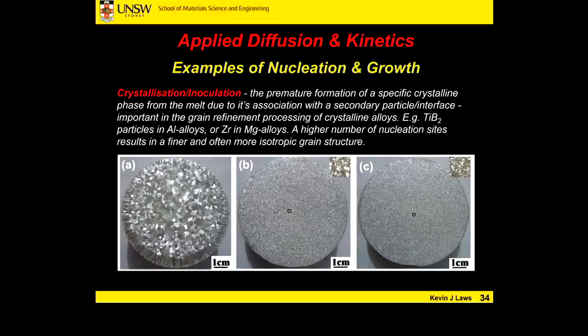So what we've got here are a couple of examples of an aluminium alloy, and we've added the inoculant crystal titanium diboride. It's typically used in industry to inoculate aluminium alloys, and we're varying the volume fraction of titanium diboride in this melt. So in the absence of titanium diboride, here's our etched microstructure of our sample. What we can see here around the outside are these columnar grains growing in.